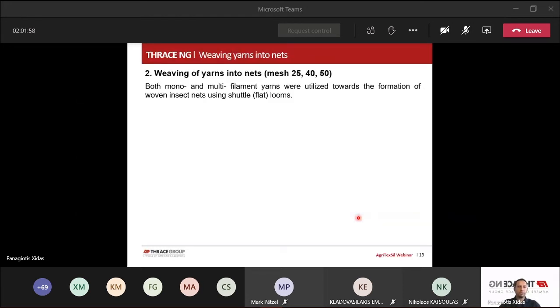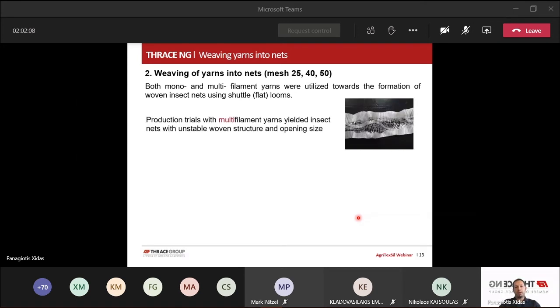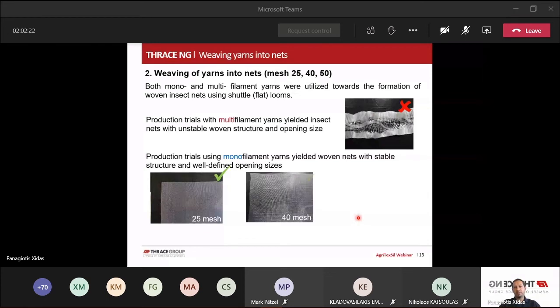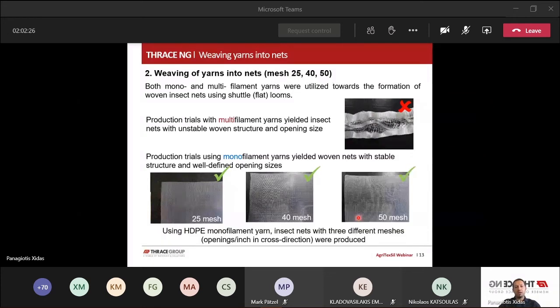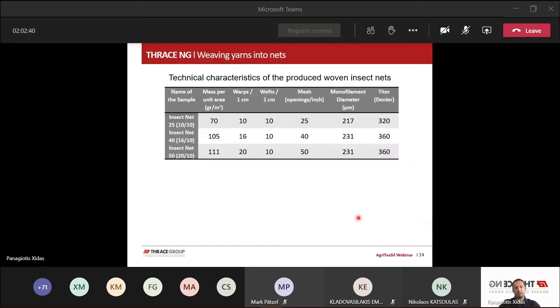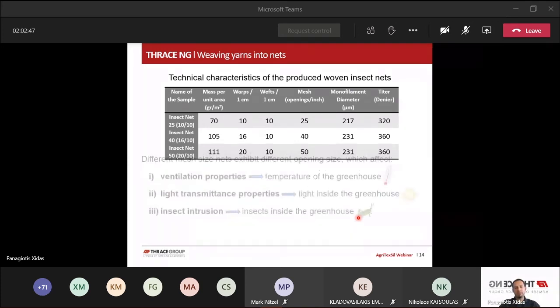So going into the second task, the weaving of yarns, we used both mono and multifilament yarns towards the formation of woven insect nets. The multifilament yarns resulted in unstable structures and opening sizes. While in contrast, the monofilament yarns yielded the woven nets with very stable structure and well-defined opening sizes. So we produced, using monofilament yarns, three types of nets: the 25 mesh, the 40 mesh, and the 50 mesh nets. The main characteristics of the nets are summarized in this table, where you can see the mass per unit area, the diameter, the titer, the mesh.